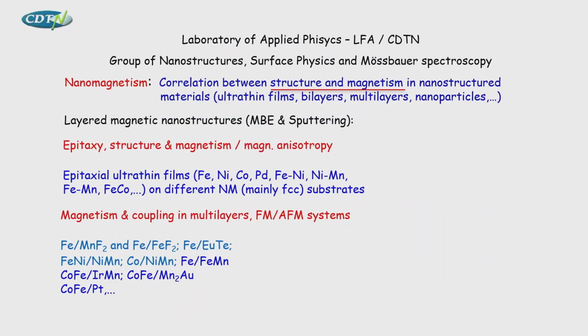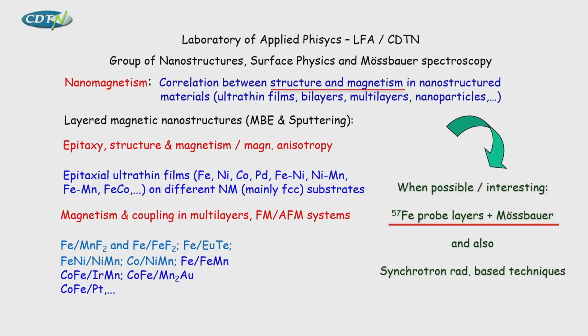What we do in our lab is try to correlate structural and magnetism in many systems, nanoparticles, multilayers, and so on. But today you concentrate on this kind of structure grown by epitaxy or by sputtering. And what we do, when possible, when we have iron, is try to use iron-57 probe layers. And also, when we get beam time, we try to use synchrotron techniques as complementary techniques to characterize nanosystems, okay?